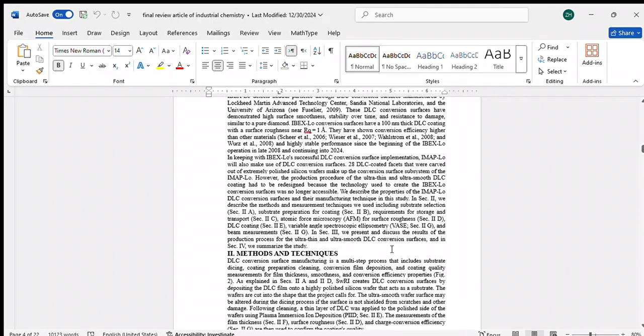After the coating is applied, the surface quality is measured to ensure the coating meets the required specifications. This includes checking the film thickness, surface roughness, and charge conversion efficiency: how well the surface can convert particles into measurable signals.